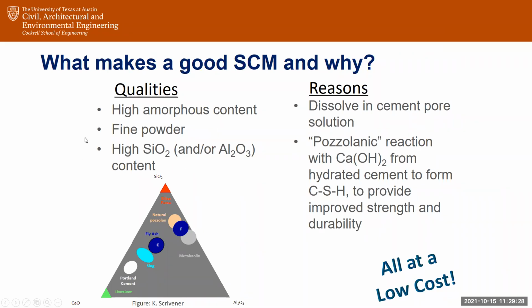So in terms of what we're looking for, there's several qualities. We're looking for a material that's primarily glassy. We're looking for a material that either comes as a fine powder from its source or can be ground into a fine powder. So it kind of looks like cement. And we're looking from a chemical perspective for something that has a high silica content and alumina content. And the reason is we want it to have a high surface area so it can dissolve in our cementitious pore solution. So we want it to be fine and have a high surface area. And we want it to have a high amorphous content so that it can dissolve in our cement pore solution as well. So we want something that's soluble, that will be reactive.